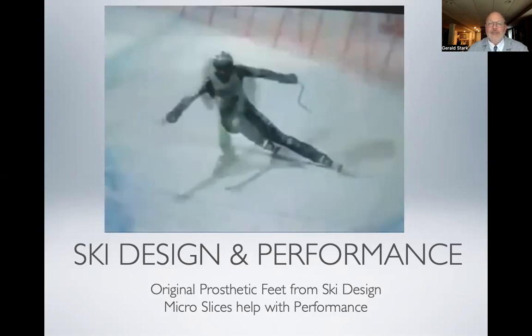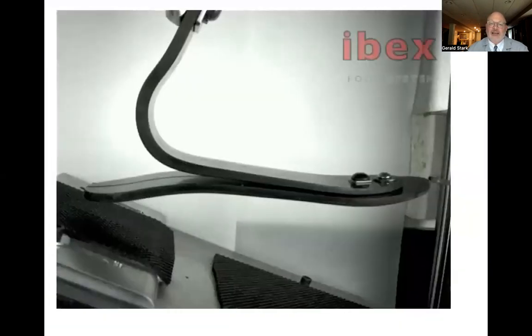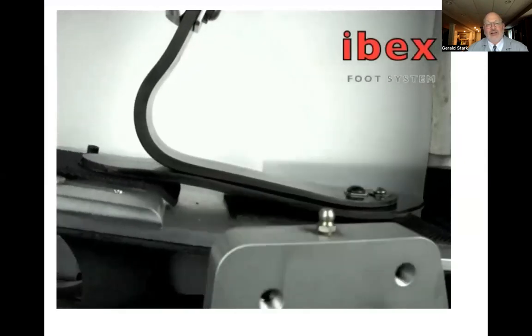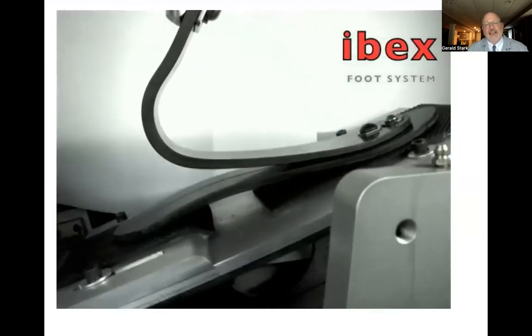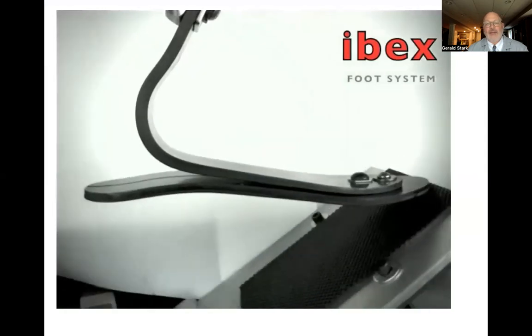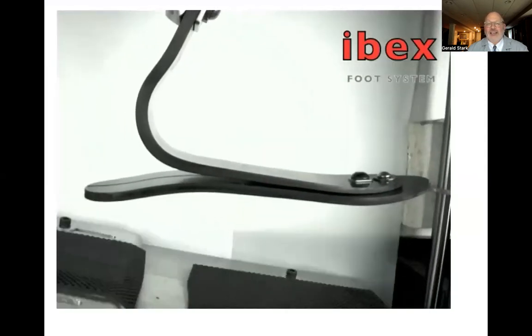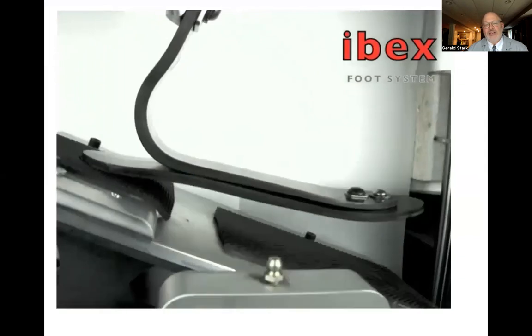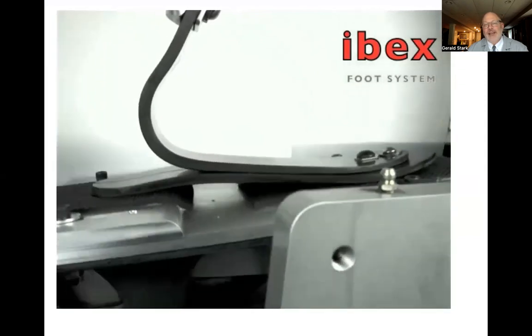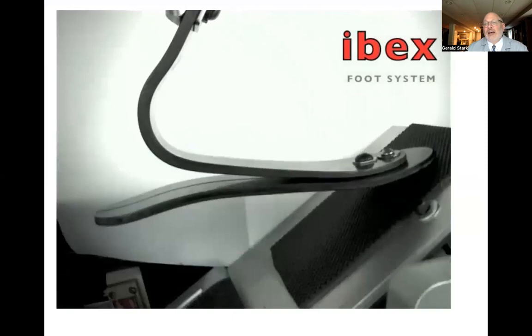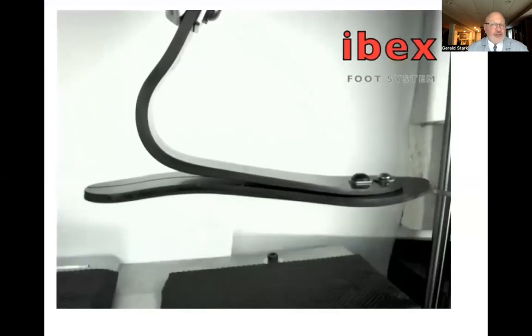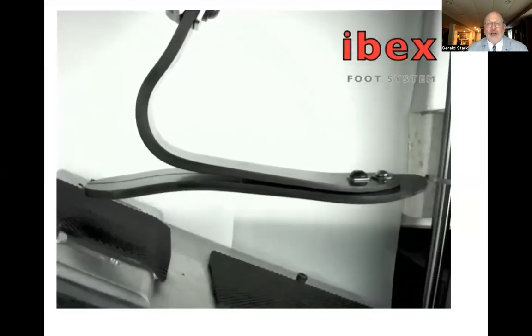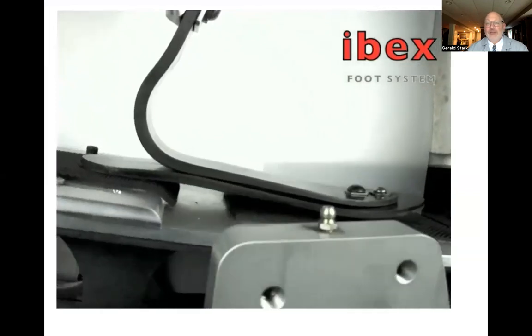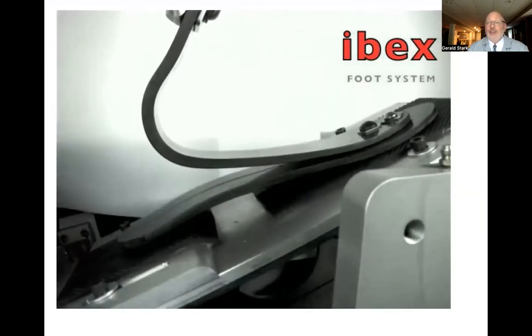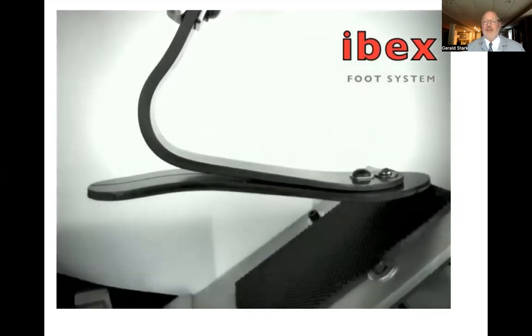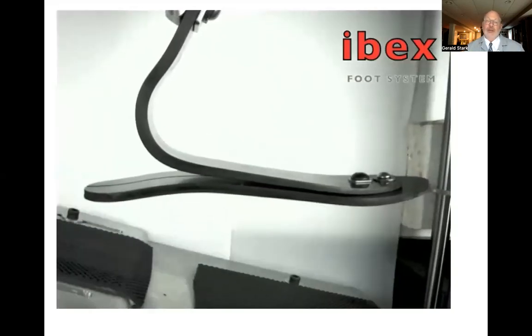They make their turns. And so in prosthetics, we expect the same thing. Here's an earlier prosthetic design. You could see just how much we expect of that blade to flex, not just in the main keel, but also the heel as well. Look how much it flattens out. And of course, we want to do this roughly at about 1 million to 1.5 million cycles per year. So when we test something for 3 million cycles, it's really just for 3 years of use that the prosthetic manufacturer is providing that liability coverage.